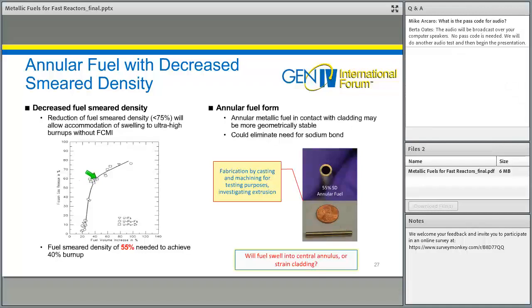But as the swelling continues on, eventually you won't have enough void space to accommodate even solid fuel swelling. Our estimations are that if you wanted to go to 40% burnup in metallic fuel, you need to take the fuel smear density down to about 55%. And so we've been doing some testing with 55, 65, 75% smear density metallic fuel. And one thing that we've noticed is a 55% smear density metallic fuel with a solid cylindrical fuel slug.